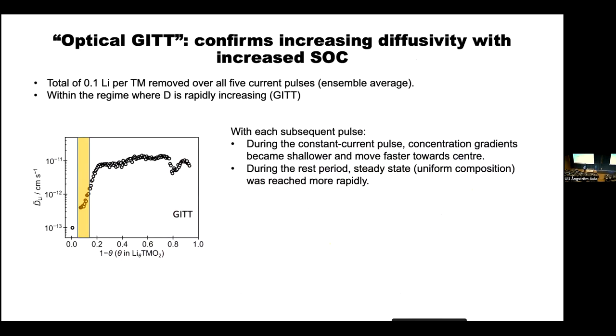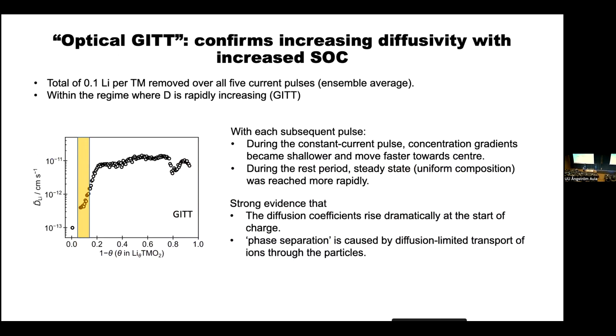What we've developed now is this optical GITT method where you can really start to look at the changes of diffusivity that come at the beginning of the first removal of about 0.1 lithiums per transition metal.